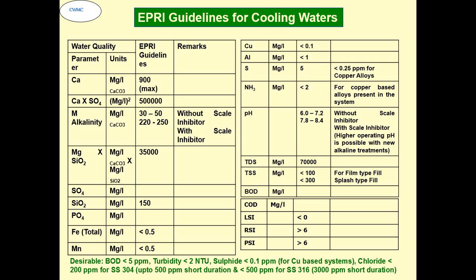Turbidity should be less than 2 NTU. Sulfide, if copper based systems are there, should be less than 0.1. Chloride less than 200 ppm for SS304, and up to 500 ppm for short duration; 500 ppm for SS316, and up to 3000 can be tolerated for short duration.